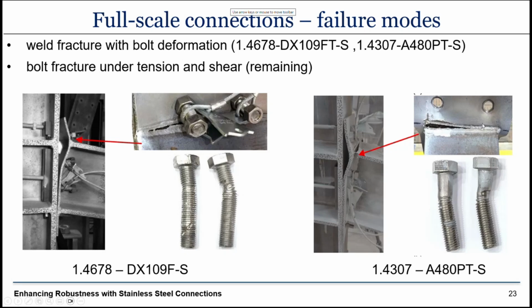Now, we did not see any weld fracture for the hybrid T-stubs, where we had the exact same weld thickness and the exact same weld consumables, and actually the same welder did both. So this is the failure mode with weld fracture. In that case, it was asymmetric, so it started from one end and progressed towards the other. For that specimen, for the 14678 specimen, it started in the middle and progressed outwards.